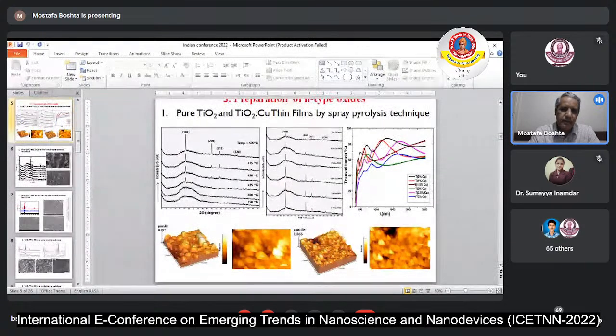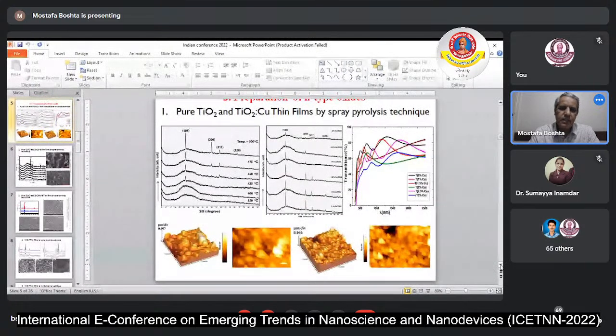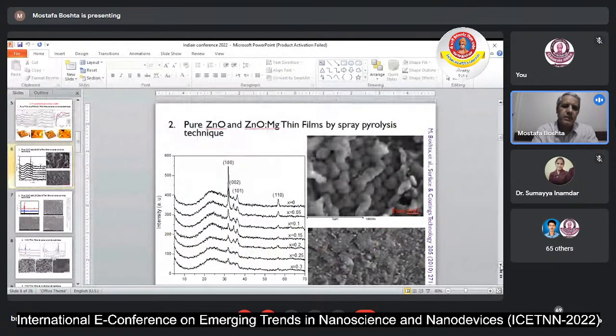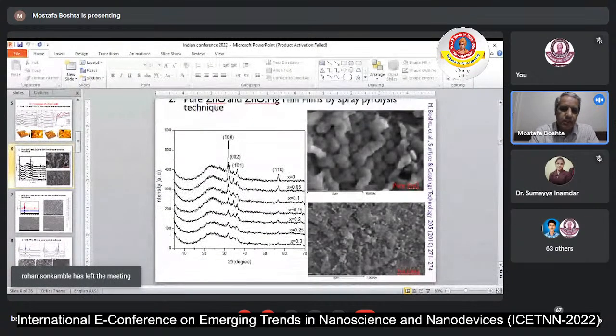measurement. After that, we also prepared zinc oxide and magnesium-doped zinc oxide thin films by spray pyrolysis. We add magnesium to zinc oxide to use it as a photocatalyst also. We need to improve and shift the energy band gap of the material.